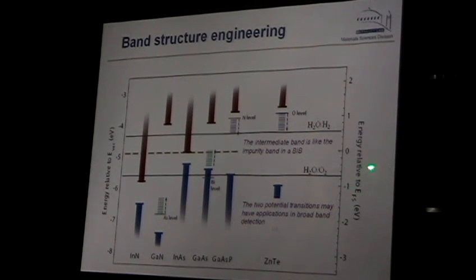For example, that's the case of gallium nitride. Conduction band is already pretty close to the redox potential. Valence band is much too far, and we know that when we put arsenic, we push the valence band very rapidly up. So by adding some arsenic, we can really satisfy the condition better, because the light of lower energy will now be absorbed, but still we preserve the proper alignment of redox potential.